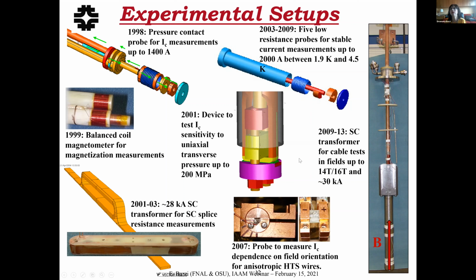Because another thing is that in these small labs, you can only go to a couple of, on the 1000 ampere level in your power supplies, because as soon as you go to high current power supplies like 20,000 amps, 30,000 amps, you need whole rooms to house those power supplies. They're very large. So what we did was to use the concept of the superconducting transformer here.